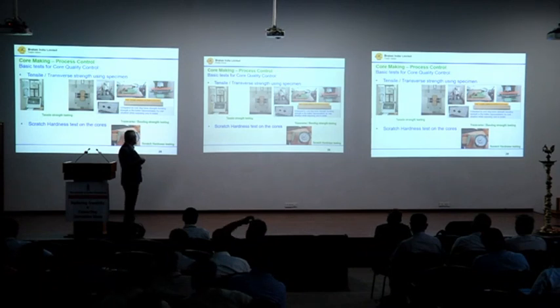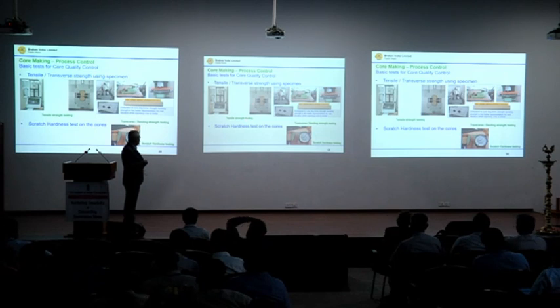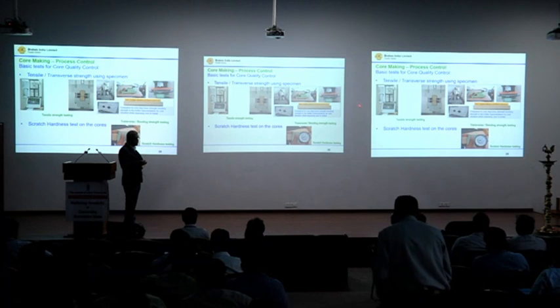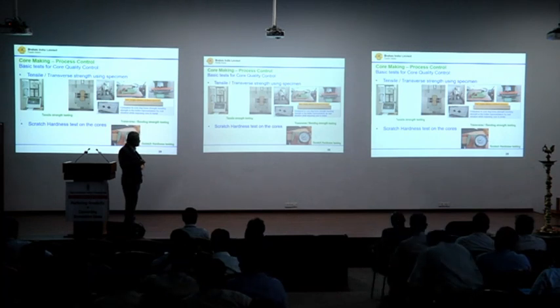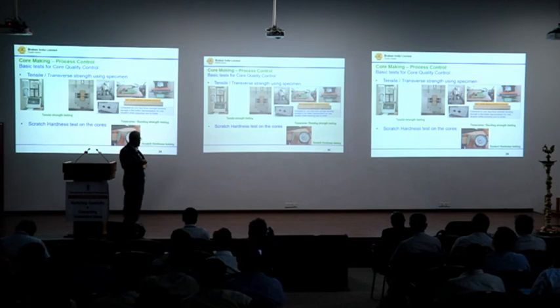So this is the sum of the tests on the cold box process: tensile strength, transverse strength. Actually, transverse strength is better than tensile, because in actual field conditions the cores are subjected to the transverse force.